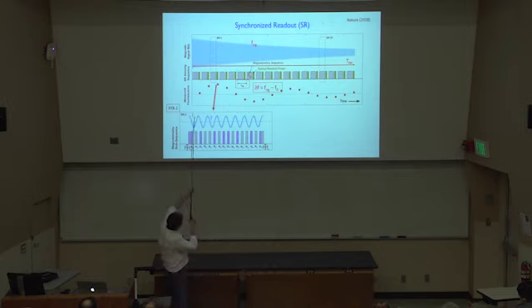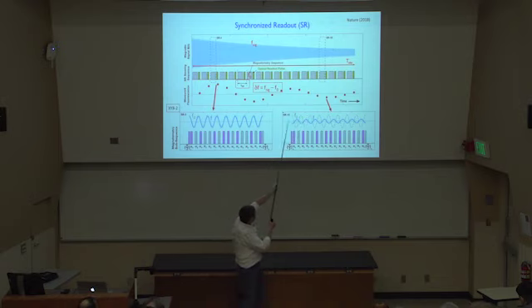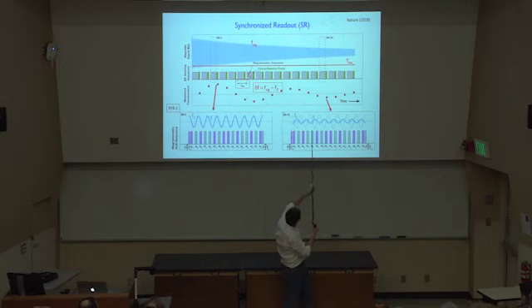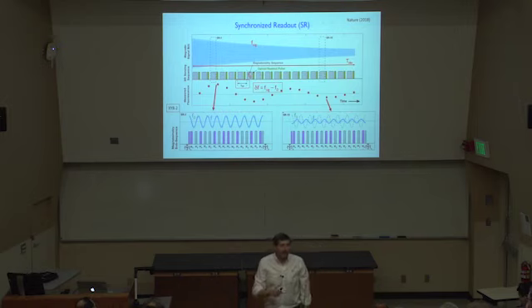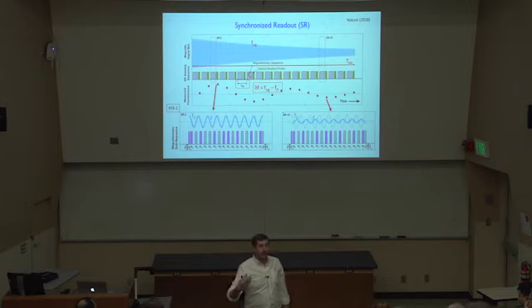So here, it's hard to see, but there's a light gray dashed line. That's showing the sensing by the NVs, and look, it's almost exactly in phase at this point with the signal. But if you go later, now the magnitude of the signal has decayed, and because the two frequencies are not exactly the same, you're now out of phase largely. And there's a beating between the two. And so since the NMR signals will typically last for hundreds of milliseconds or seconds, because the coherence times of the proton spins can approach a second, you can now be limited when you do NMR, not by your sensor, which you have the synchronization to do everything in phase, but by the decay of the signal that you want to sense, which is the best you can do.